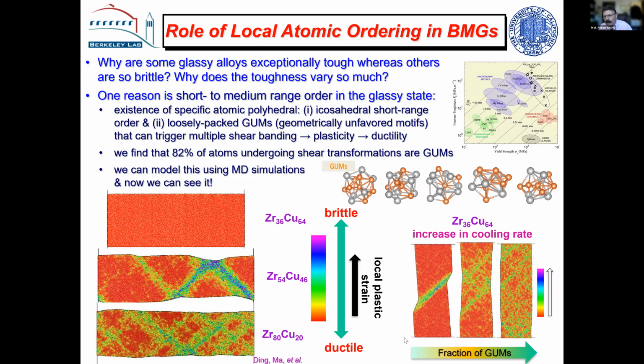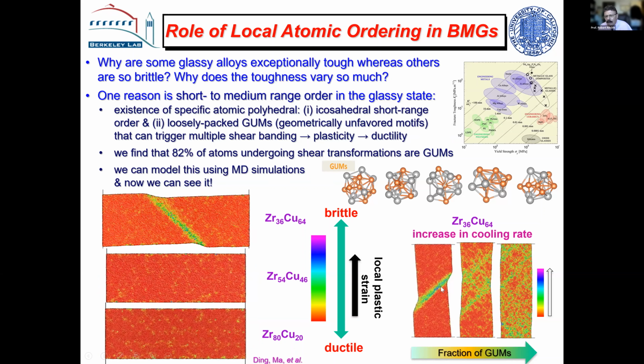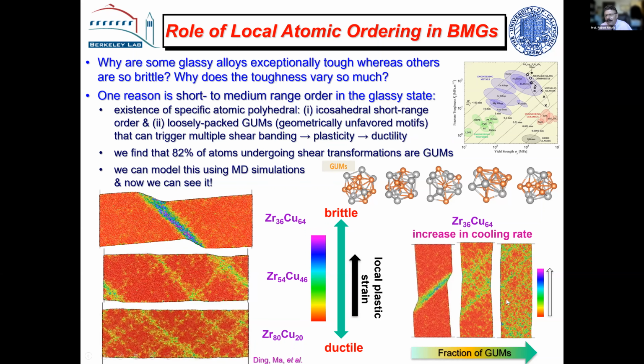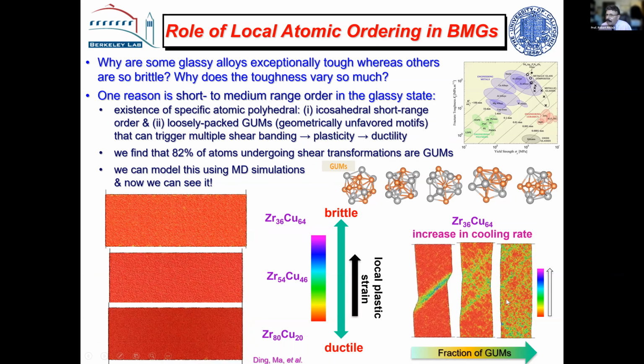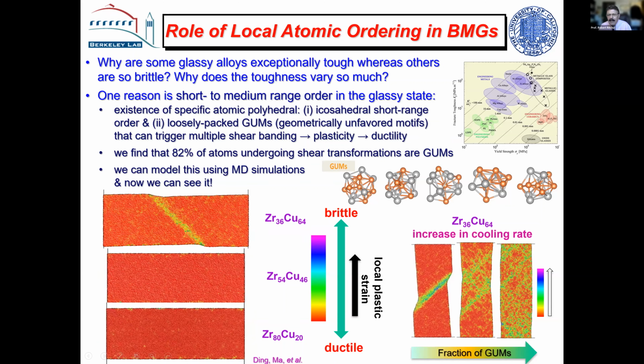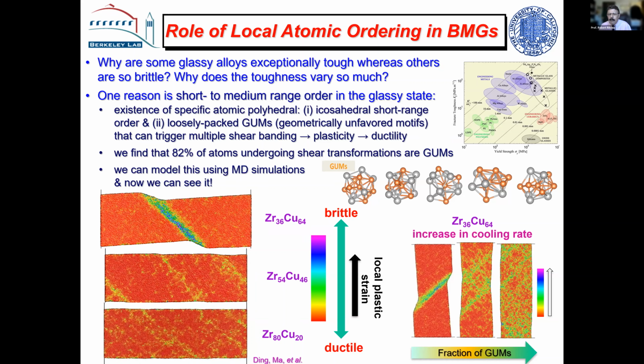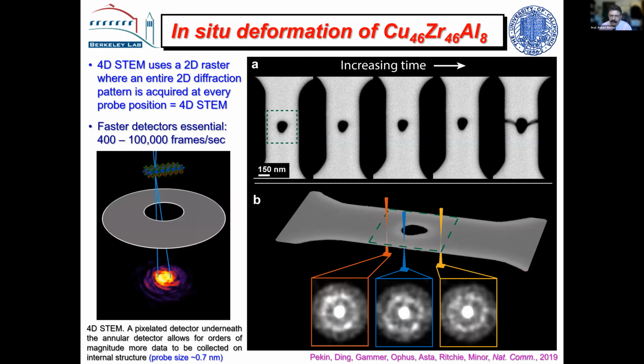And you can change them with cooling rate. The irony is that when you have a slow cooling rate, you get a brittle material. When you get a fast cooling rate, you get a ductile material. Everything's back to front. So we tried to see if we could prove this by using electron microscopy, trying to look at some way of seeing that. So we could try and find that where the shear bands form are in regions where there's less icosahedral five-fold symmetry. And this is work with Andy Minor at the National Center for Electron Microscopy.